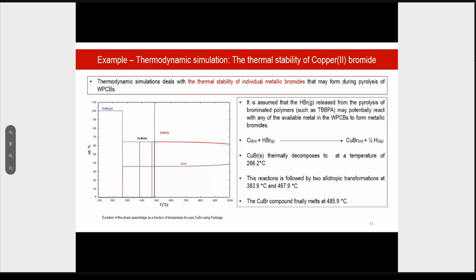The idea here is that we are supposing that the hydrogen bromide released is going to react with copper to produce copper bromide. In FactSage, the FactPS database, or the pure substance database, contains the thermodynamic description of almost 300 brominated compounds. One of the important aspects to consider is that the thermodynamic simulation of the pyrolysis process using FactSage is very challenging, since pyrolysis is typically performed in an open reactor. Open reactor means that the evolved gas is constantly removed from the system, which impacts the overall composition of the system. So one of the approaches that we use to simulate this system is to equilibrate the condensed material with a given amount of inert gas, which might be argon or nitrogen, and then remove the equilibrated gas phase from the system. This type of calculation is performed using a mode called the open mode calculation.